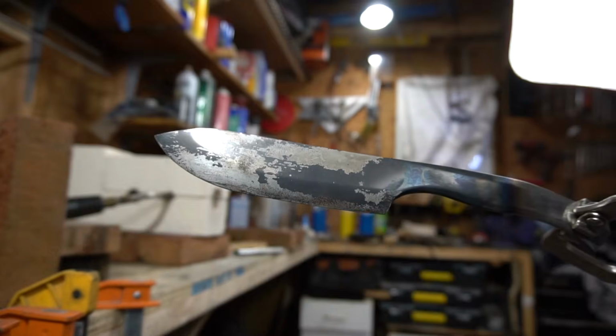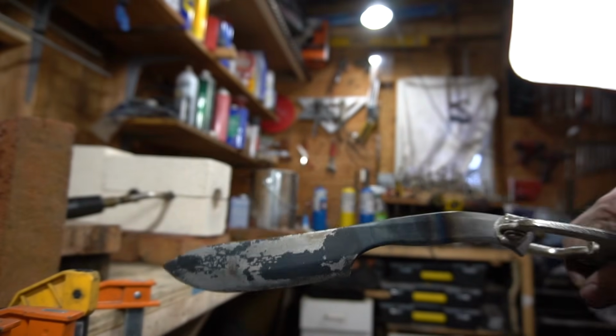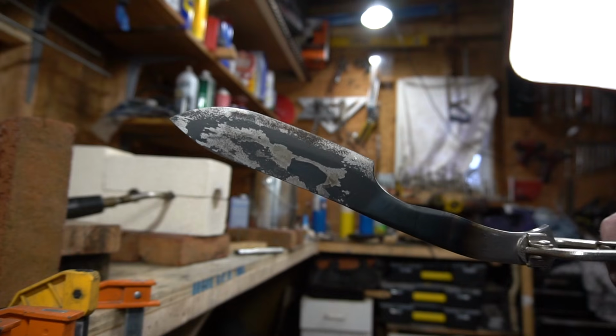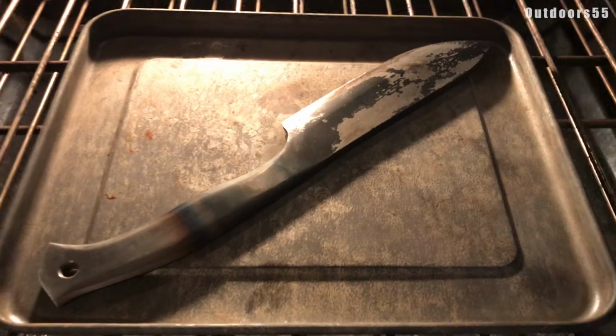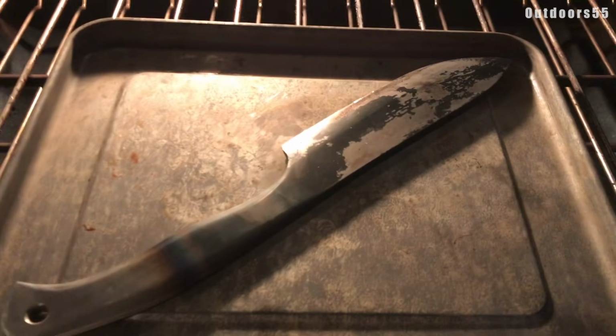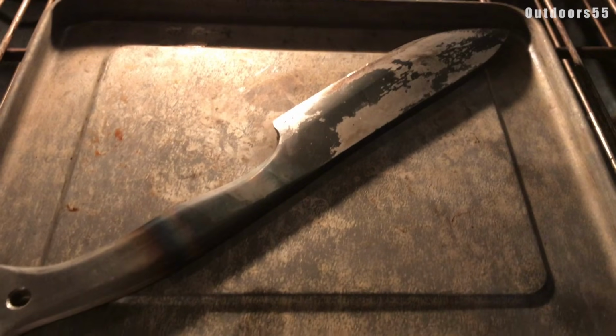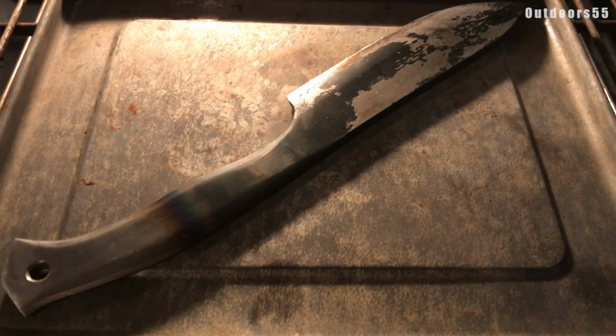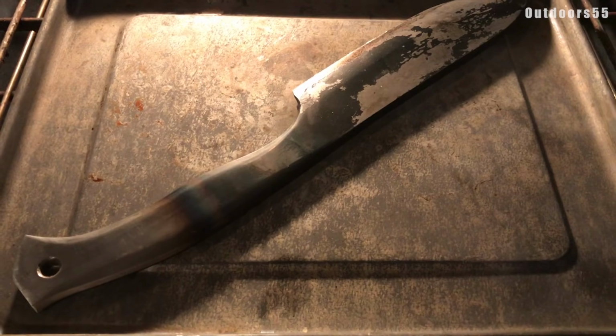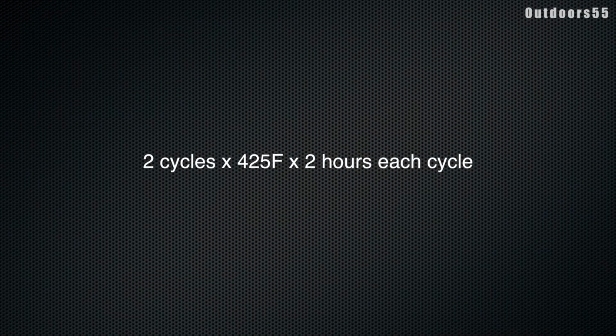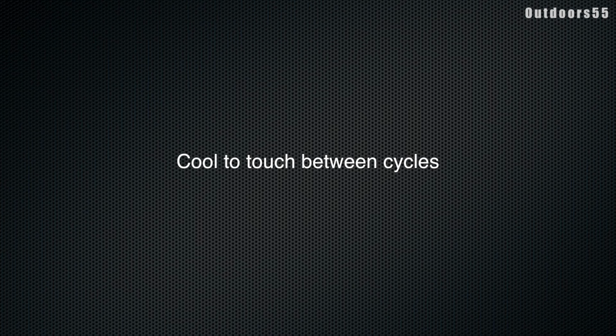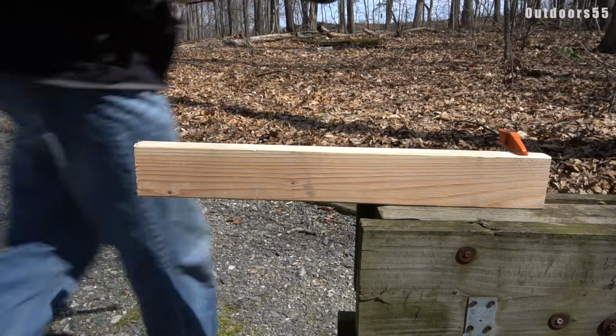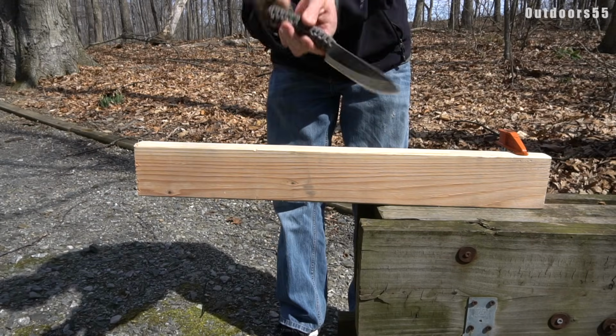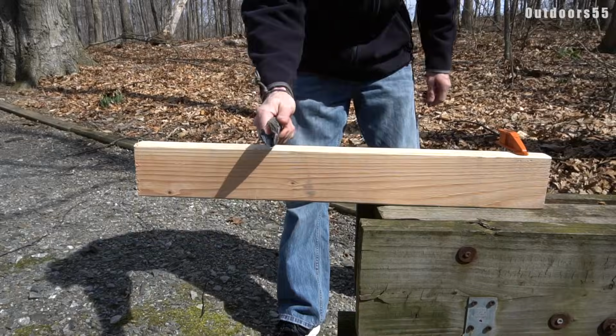Now we have hardened the blade, but at this point the blade is too hard and can crack or shatter if you went ahead and tried to baton through a piece of wood, or even dropped it onto the ground. So in order to bring the hardness down, we need to temper the knife in a home oven. I usually temper 1080 for 2 cycles at 425 degrees Fahrenheit for 2 hours each, allowing the knife to cool to the touch between cycles. Tempering will bring the hardness down and increase the toughness of the blade, which I'll demonstrate at the end.